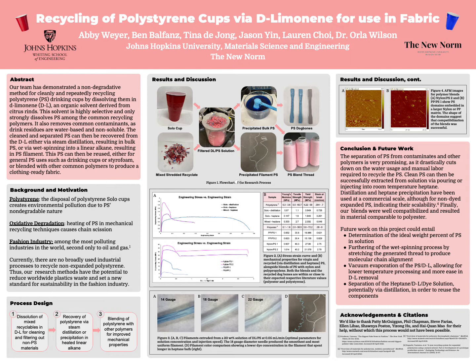In the rightmost image in the optical section, you can see that we've produced filaments of different colors. We found that the longer the thread spends in the heptane, the lighter in color it becomes as more dye is leached from it. We believe that this is correlated to the D-limonene leaching as well, as the lighter threads were stronger and firmer than the more vibrant ones. A side benefit of this is that the lighter threads were easier to dye over with whatever color you may desire. Finally, we performed AFM on our blends.